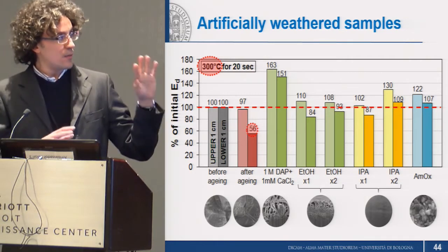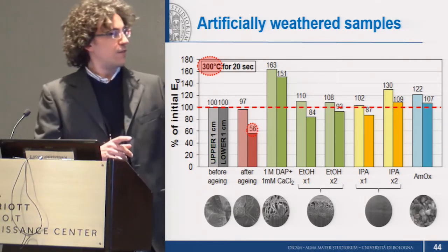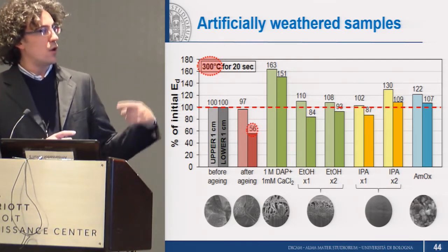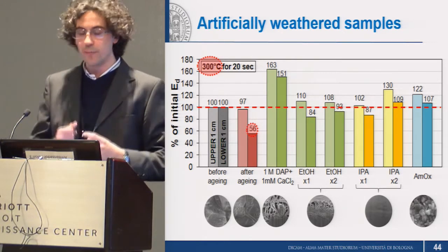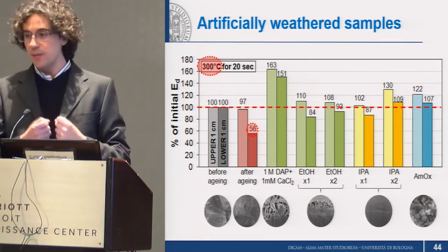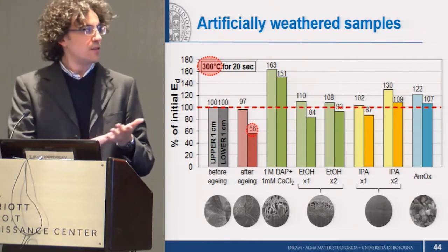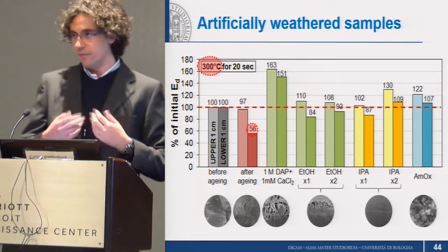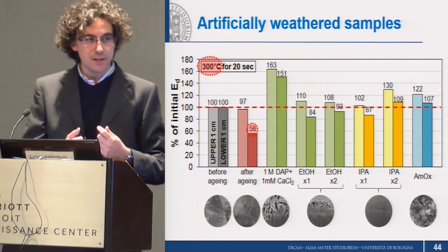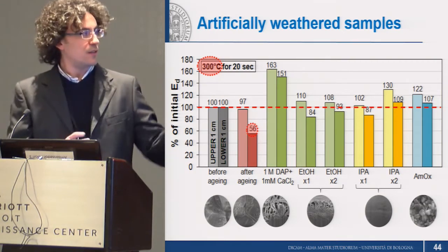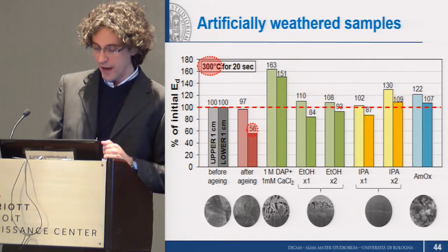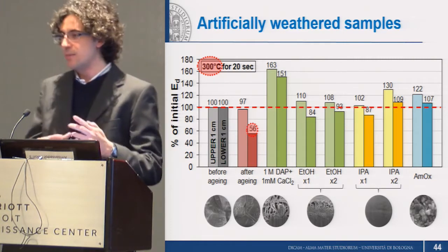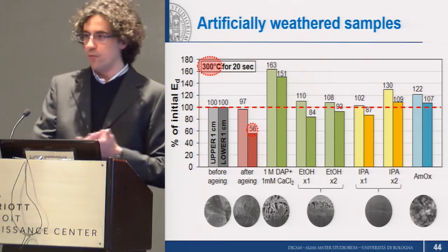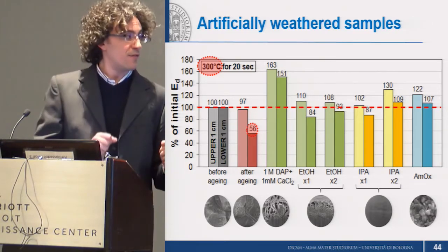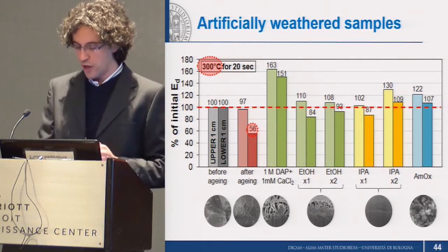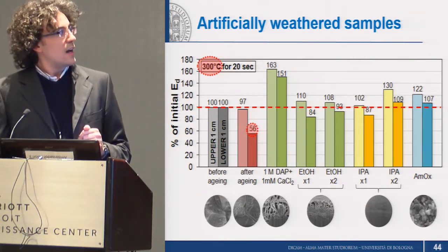And as you can see, in terms of simple mechanical improvement, our first original formulation, the one with a coarse, porous microstructure, in spite of being porous, so not being able to provide a good acid resistance, was still able to very strongly improve marble mechanical properties. This is because it's easier for this formulation, with a higher concentration, to fill the cracks. So depending on the goal that you want to achieve, whether it's more a mechanical binding effect or acid protection, one formulation may be preferable over the others.